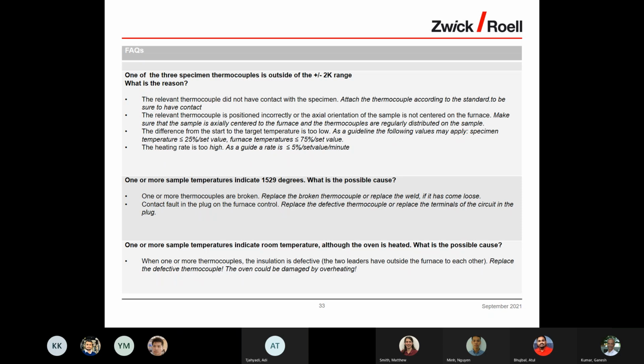Contact fault in the plug on the furnace control. Replace the defective thermocouple or replace the terminal of the circuit in the plug. One or more sample temperatures indicate room temperature, although the oven is heated. What is the possible cause? One or more thermocouples in the insulation are defective. Replace the defective thermocouple. The oven could be damaged by overheating. Be careful.